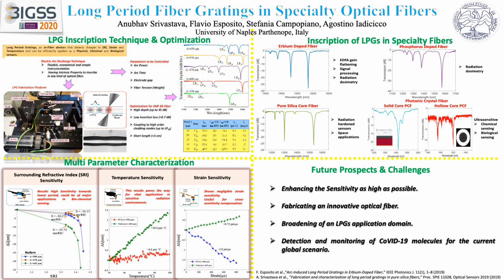You can see here the fabrication platform in an inset, a state-of-the-art computer-assisted step-by-step inscription platform for long period gratings. We can see that two electrodes are fixed by customized holders. The electrode holders are arranged on separate XYZ manual micro stages, allowing a high degree of freedom towards alignment of the fiber and the electrodes. Moreover, two customized holders kept at a distance of 20 cm keep the optical fiber suspended between the electrodes.